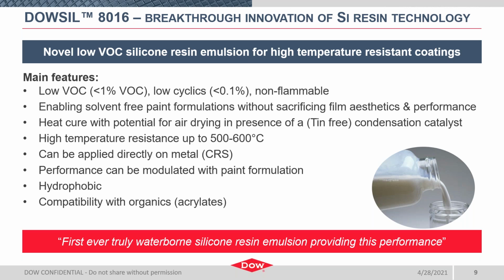Among the main features, I'll first reiterate its EHS benefits. It's very low VOC and truly waterborne without solvent inclusion. It also contains that low cyclic threshold of less than 0.1% and has a high flash point, which omits the flammability label on the SDS. The 8016 doesn't necessitate the use of added coalescent solvents in paint formulations, still securing good film aesthetics without that, and subsequent film performance, which allows for even lower VOC formulating.